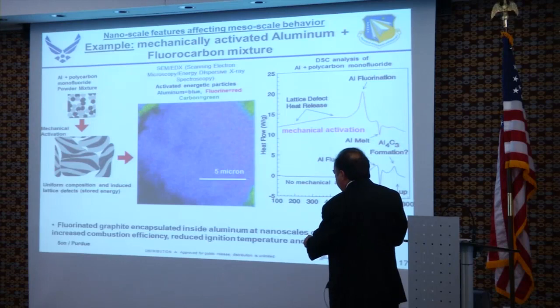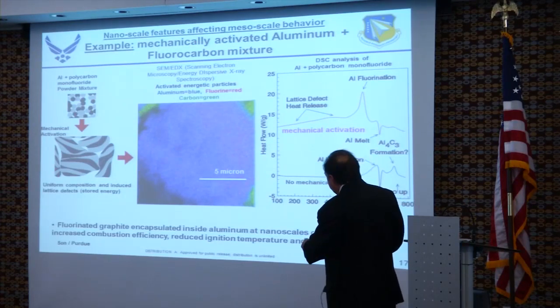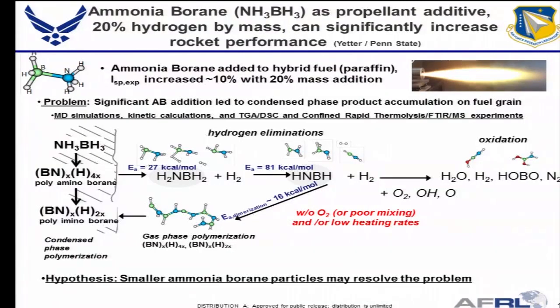connecting atomistic scale modeling to mesoscale modeling. At Penn State, they added ammonia borane to a hybrid fuel, paraffin, and in that laboratory scale hybrid motor, specific impulse increased 10% with a 20% mass addition. But these are micron-sized particles. But what will happen when they increase more than 20% is that there is a crust on the grain and it stops the regression rate of the grain. So they decided to find out, because the kinetics is not known. So how can they do that?